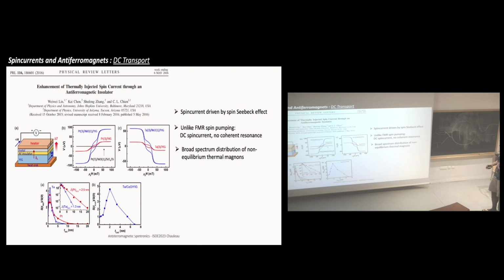I don't remember if Michel talked about that last week, but you can use thermal effects. This is what they call the spin-Seebeck effect. Then you have a heat gradient, and because you have a heat gradient, you have an imbalance between thermal magnons, and then you have magnons, basically a magnetic current which goes through. So this is what they are doing here. They heat up YIG again, so then you create a heat gradient in that direction and also a spin-Seebeck effect. And this is the same as what they did.